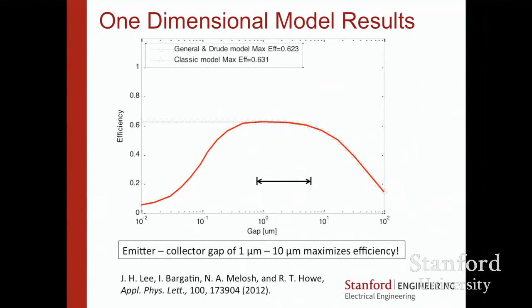The efficiency, 60%, is an idealized 1D model. It's the area where we want to operate. We don't want to be where the Russians were, which was over here at 100 microns, losing a lot of efficiency to space charge and having to do a plasma and not really recovering it. And if we get really close, then we also get thermal shorting. So that, I think, was a contribution to set the rules.